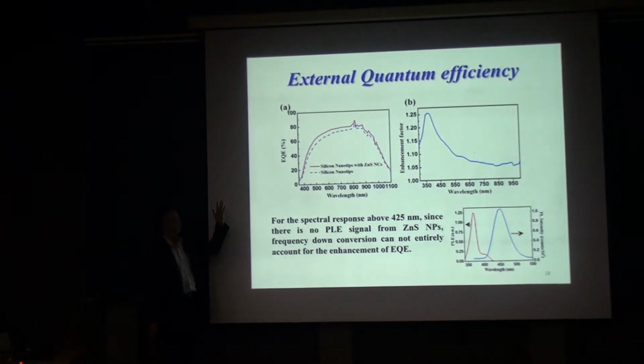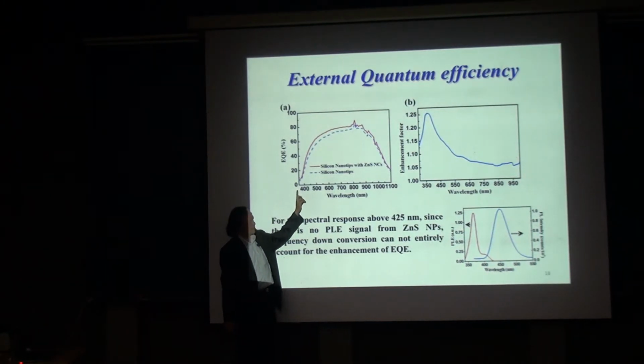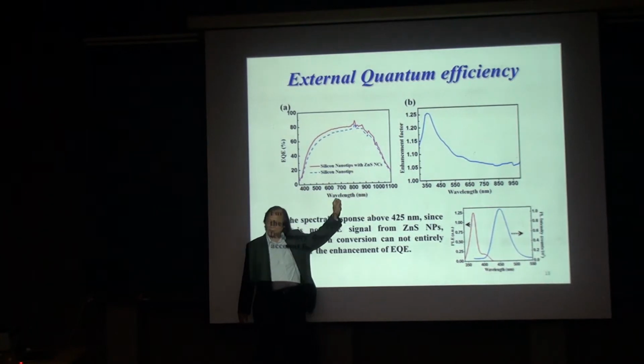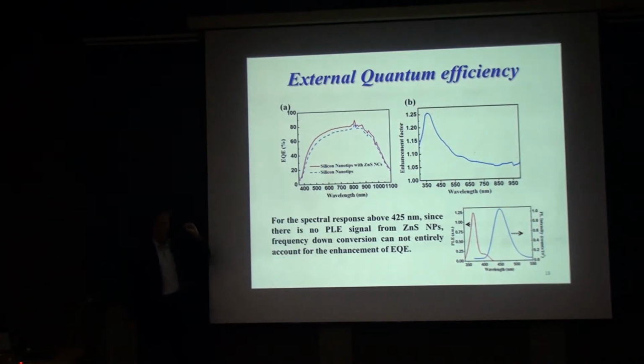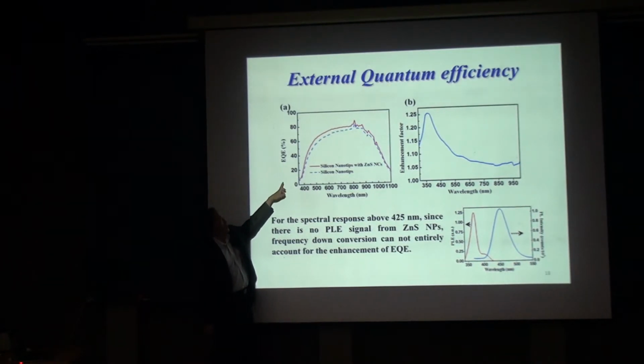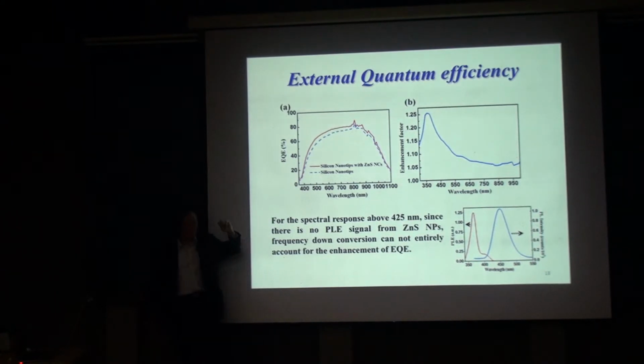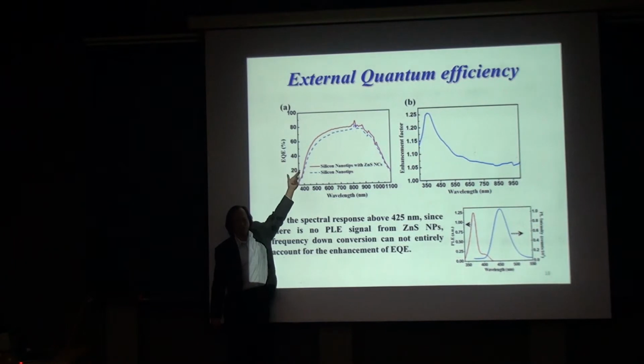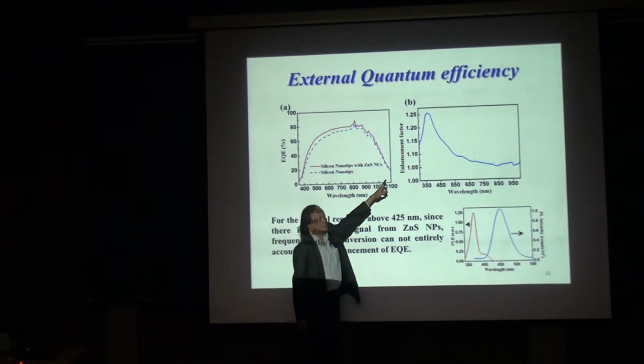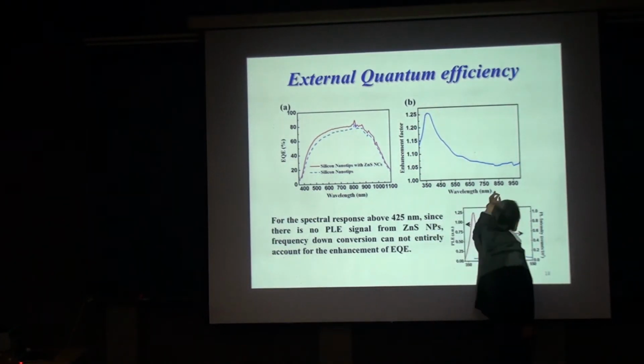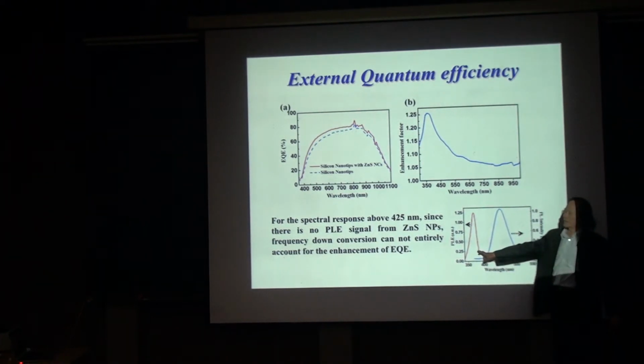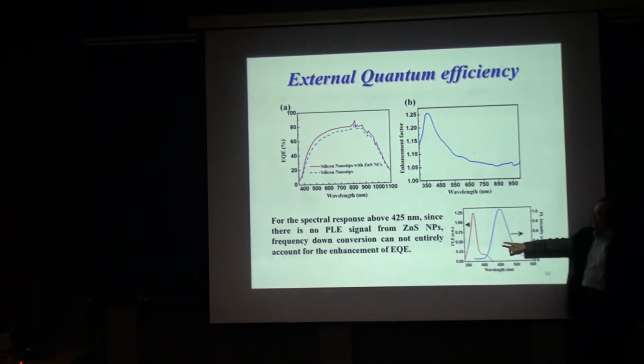Okay, and this is the external quantum efficiency, which tells us the response versus the incident photon wavelength. You can see after the deposition of quantum dots, the efficiency is enhanced. And then we divide these two curves, and we get a peak position. This peak position is consistent with the absorption peak of the zinc sulfide quantum dot.